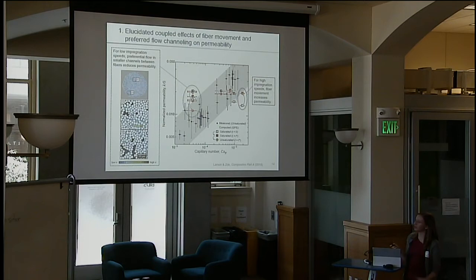So the first thing we've looked at is how the fluid flows in the fiber beds and how this influences fiber movement. This is important because the flow speed through the fiber bed influences the types of bubbles that will form during the impregnation process. And so we want to be able to predict and control this flow speed. And being able to control it depends on being able to predict the permeability. And often the permeability of the fiber bed is very difficult to actually predict because it changes depending on the speed at which you infiltrate the fiber bed. And so we wanted to really figure out why this is happening so we can develop models to improve this process.